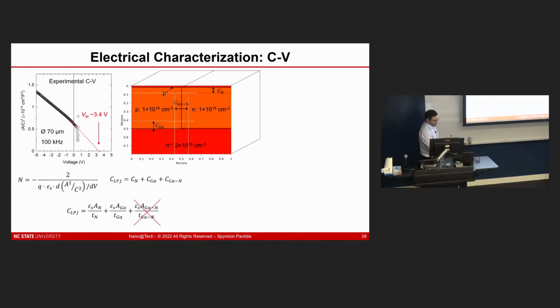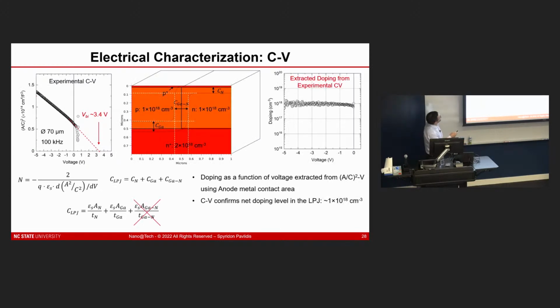And I will briefly show this so I make sure I have enough time for the next section. We also did CV on these devices, and from the slope of the CV, we're able to back out what the doping concentration is inside here. Now, electrically, we can also see that we've got 1E18 doping in these regions, which is in agreement with the SIMS results. So we have a couple of ways of showing that we have consistency of doping incorporation within these structures. Yes, this CV analysis matches with SIMS as well.